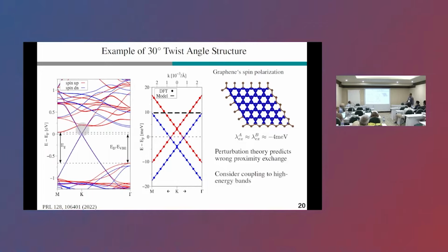If you consider perturbation theory, you would expect that the Dirac states would couple to these energetically closest spin-up substrate bands. However, if you would do that, then the spin-up Dirac states would be pushed to lower energies because energy levels that are coupled repel. However, this is not what you observe in the DFT calculation, and it's actually rather the coupling to high energy bands. And in particular, you will find such a pronounced anti-crossing of spin down Dirac states with substrate bands. And this is in fact pushing the spin down Dirac states to lower energies. Yeah, so the coupling is here.